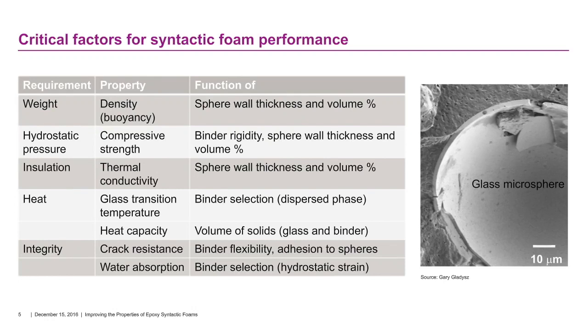So when we talk about weight and actually weight reduction, that means we have to look at density issues and buoyancy if that's required. It's a function of the sphere wall thickness, the loading level. Loading level also comes into play regarding the ability of the foam to withstand hydrostatic pressure, basically the compressive strength of the foam. The shape of those spheres, the nice round shape, obviously is going to give you very good resistance to compressive forces, but the wall thickness is equally important.